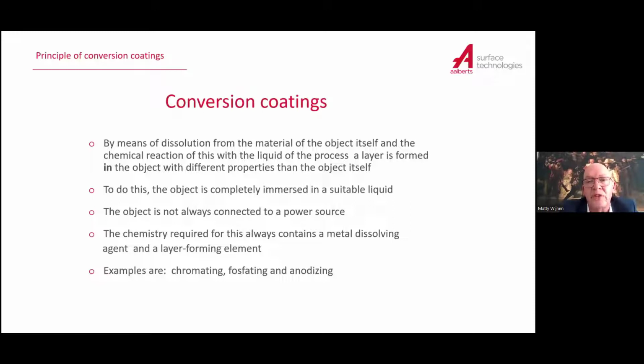And then they form a salt, and that salt is a layer which is formed on the part. Think about chromating. When you chromate, you put your aluminum part in an acid solution, and your aluminum is dissolved. The chrome salt is reacted with the aluminum and forms aluminum chromate on your product. And that's a totally different process.